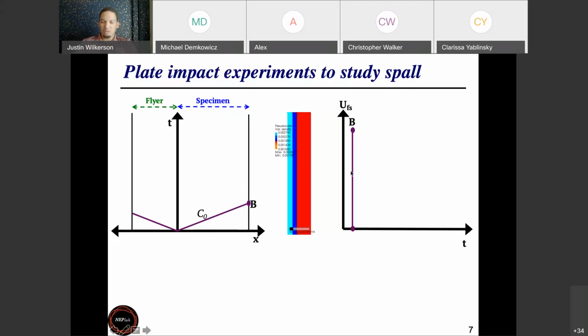And so that shows up as this. What I'm plotting here is the free surface velocity, which is typically what we are measuring in the experiments, as a function of time. That's measured from the back face in the XT diagram, or from this back face in the simulation. So you get this jump and you come to this point B, which relates to point B here in the XT diagram.